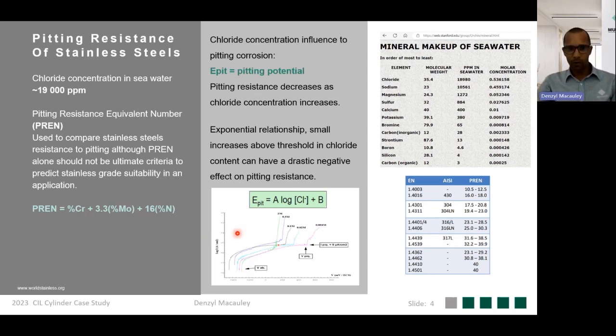Now, on the graph, as you can see in the middle below the screen, we couldn't understand why all of a sudden, now we've been supplying the same cylinder, same material of construction for the past 10 years, this aggressive pitting corrosion has started. What we concluded or assumed could be the case is that the solution was operating in this region over here. And just as the chloride content reached a certain threshold, there was an exponential decrease in the pitting potential. Further tests are still ongoing, but that is what we are trying to conclude.